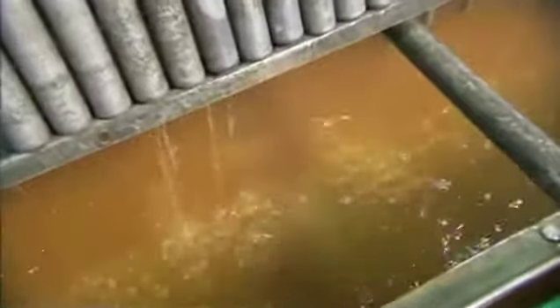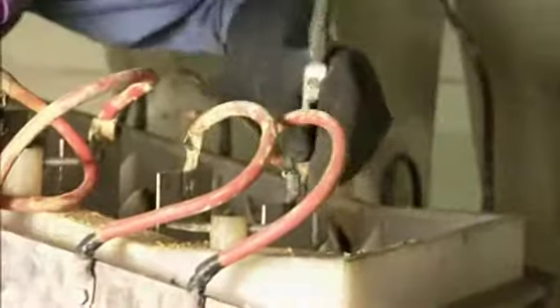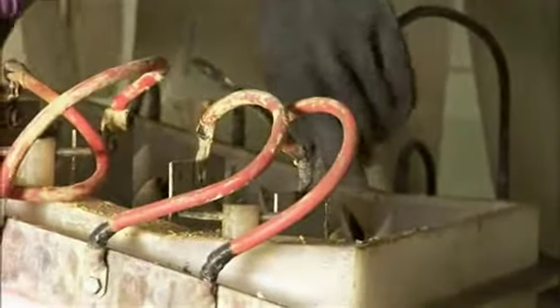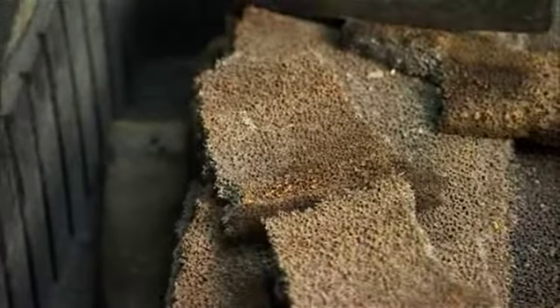We would then take that solution, pump the solution out and spin it, make sure it's homogeneous, and take a sample of that solution. And after we remove a portion of the water, we pump it over into a plate-out tank where we actually plate the gold out of the solution onto cathodes. The basic concept is that you have a cathode that's charged electrically, and we have the solution that passes through the cathode, and over the course of several days, all the gold attaches to the cathode and leaves the solution. The solution is checked continuously until it is totally free of gold. The cathode is then removed and dried in an oven.